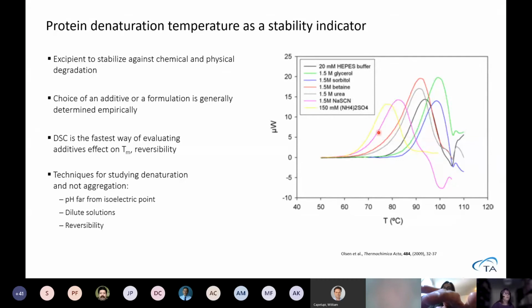So you will both need to look for TM and also if there is aggregation occurring after the denaturation. Nevertheless, it's a quick way, but now if we would like to look at what happens if you isothermally store, I can also say that DSC in many cases need to be diluted below 10 milligram per milliliter to be able to put into the DSC, while we said that many of the formulation will be plus 100 milligram per milliliter, so we need to dilute them to be able to measure.